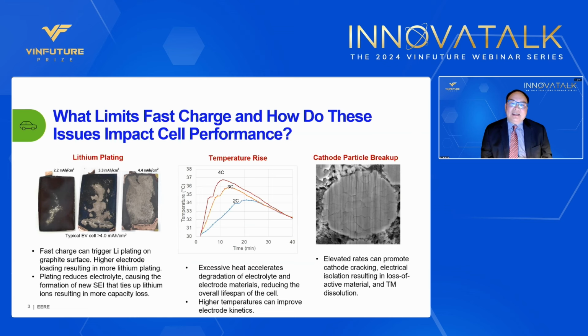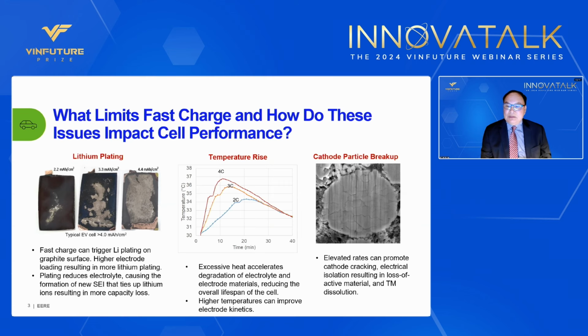And again, the second thing that can happen is temperature rise. At faster charge, at 4C and 3C and 2C, you can see the temperature rise accordingly. One good thing about high temperature rise is that it can improve electrode kinetics. It also may reduce the overall lifespan of the cell because it accelerates degradation of electrolytes. And the third thing we like to talk about is potential, though rare, cathode particle breakup. Elevated rates can promote cathode cracking. Electrical isolation results in loss of active material and transition metal dissolution. So those are the limits of fast charge.